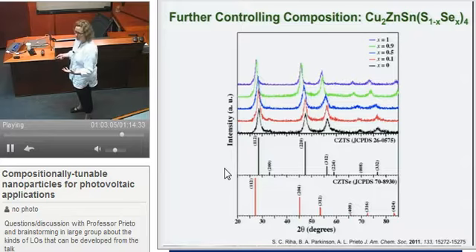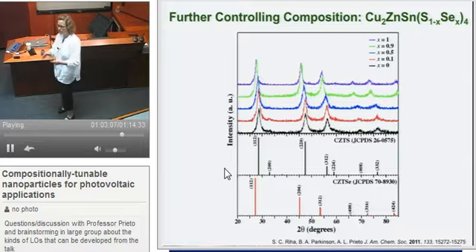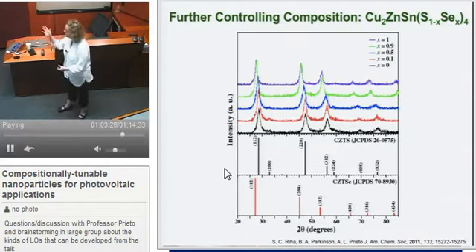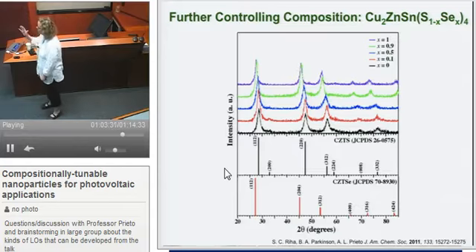This follows Vegard's law, which basically says if you take a unit cell and you put in an atom of a different size, the lattice parameter should change in a linear fashion. So you can, in theory, use the lattice parameters to calculate composition. This is a cool exercise; I usually have students do it with sodium chloride and potassium chloride, because they have the same structure. But this is the exact same idea. And the fact that it shifts in this linear fashion was an indicator that we were actually getting both elements into the same particle.